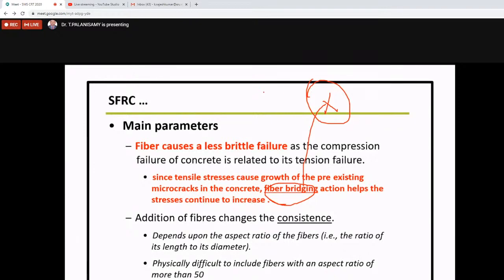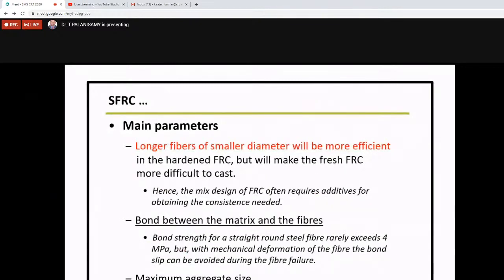Then the addition of the fibers changes the consistency depending upon the aspect ratio of the fiber, the ratio of the length to the diameter. It is physically difficult to include a fiber with an aspect ratio of more than 50, because the concrete contains about 70% volume of aggregate particles which cannot be penetrated by the fibers. That is the problem. We already have coarse aggregates, so it is unable to disperse the fiber in between the coarse aggregate. That is another issue.